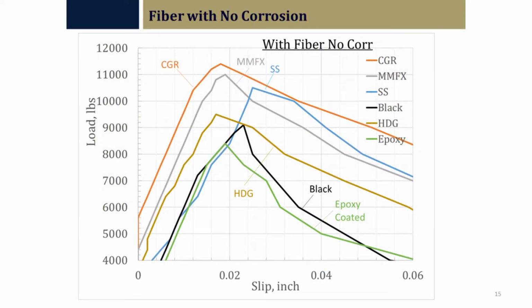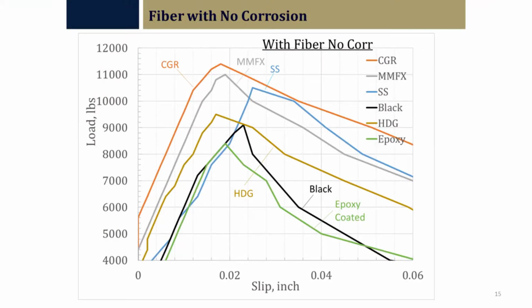Test result. You can see you want to be far left and high. So looking at this, you have a load of almost over 9,000 pounds where you're starting to separate from uncoated and epoxy. So that's hot dip galvanizing in the gold, stainless steel in the blue, MMFX, and continuous galvanized towards the top there. So this is with fiber and no corrosion. So pretty good results. You want to be, again, far left and high.